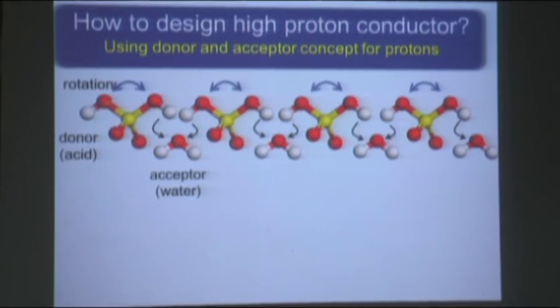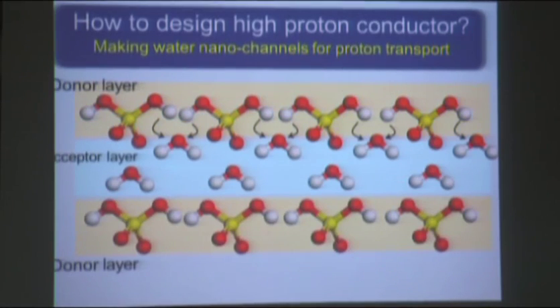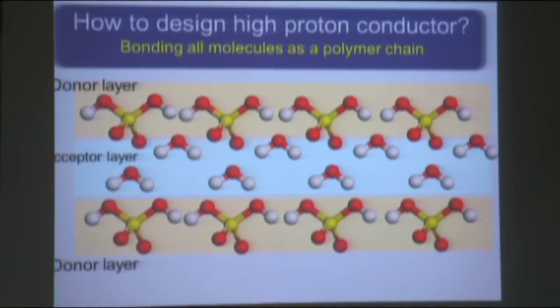So here is the schematic view. Sulfonic acid and waters. The sulfonic acid is a donor, and the water is an acceptor. This proton can be received by the water. This proton, the white one, is a proton. Then, if you can arrange this, maybe you can have a highly proton conductive material. So if we can make a nanochannel, a water nanochannel like this, donor layer, acceptor layer, donor layer like this, maybe a high proton conductive material, but you need to bond each other.